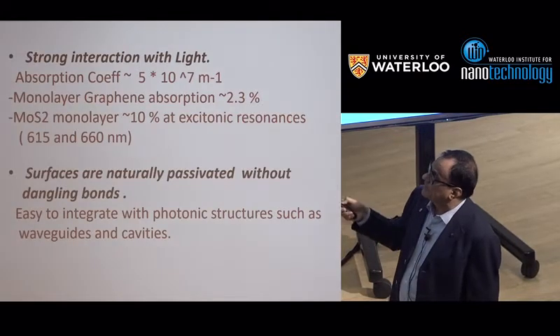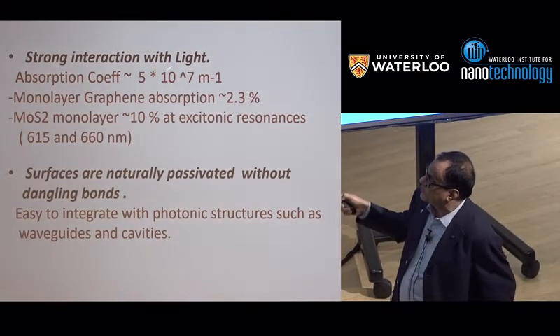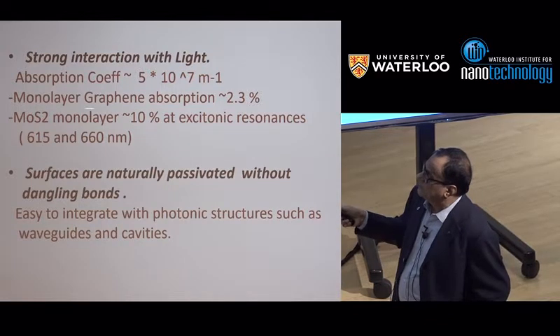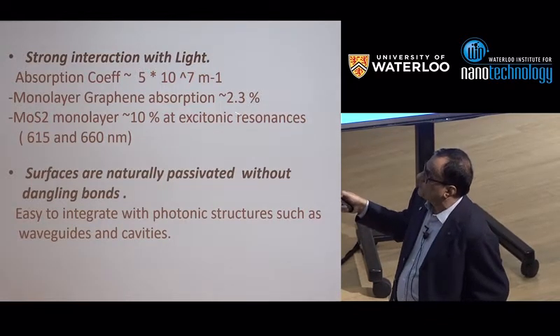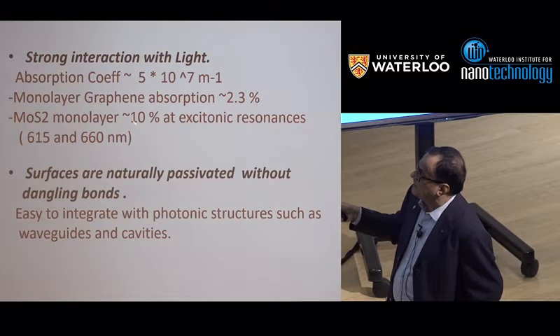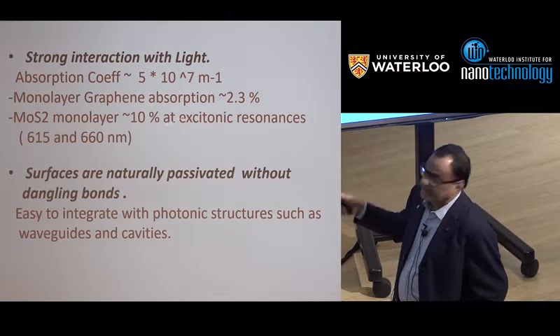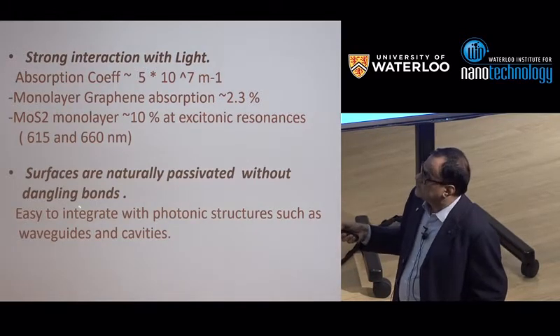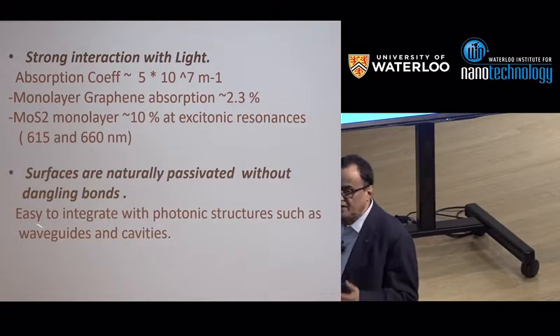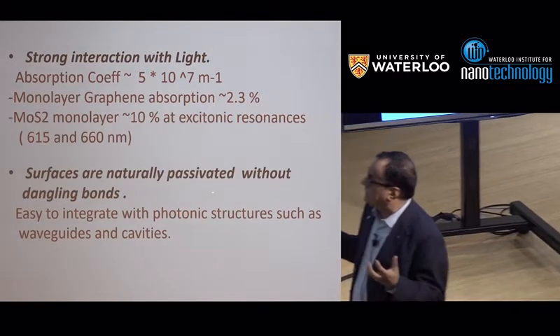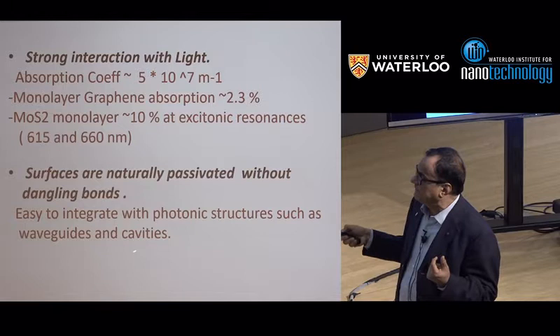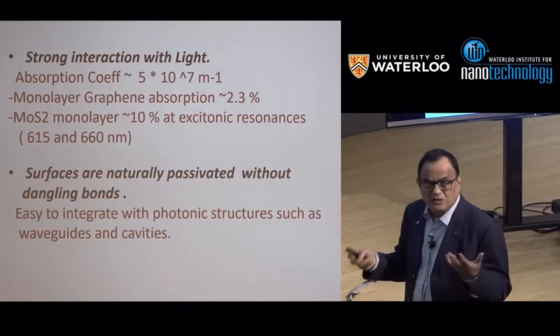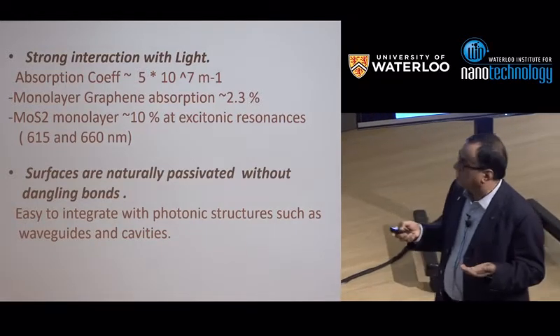You have strong interaction with light. You can see the absorption coefficients are large, and even a monolayer of graphene absorbs 2.3%, and a MoS2 layer almost 10% at excitonic resonance. And this is something which has given rise to a whole field to couple them with waveguides and cavities, because they are naturally passivated without dangling bonds.